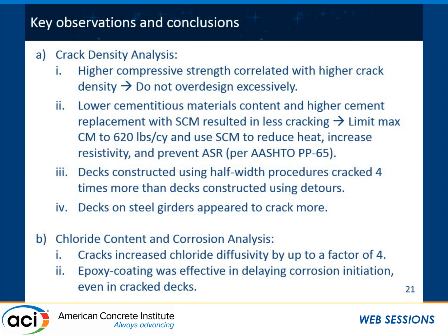Well, there could be a range of reasons. One is that when you do a half-width, first of all, I appreciate the question. When you do a half-width construction, you have the constant vibration of the deck as you are placing the concrete. And especially in the cases where your slump is a little bit on the higher side, you could promote settlement cracking right on the rebar. So that's one reason. There could be other reasons.